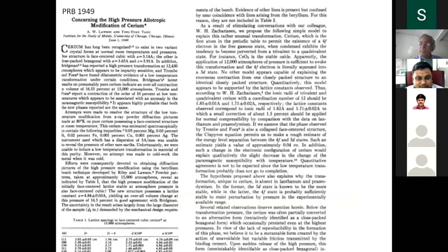Now, actually, there are enough indications of this phenomenon even 100 years ago. The famous physicist Bridgman, the father of high pressure physics, was studying all the elements in the periodic table under pressure. He took up cerium metal. When he studied cerium metal, he found there is a volume collapse by applying pressure of something like 12 kilobar. Then he found that the pressure at which the transition takes place varies from one lot of cerium to another lot of cerium, so he did not understand it at that time. Subsequently, other groups confirmed, yes, there is a volume collapse of cerium. So it was left like that.